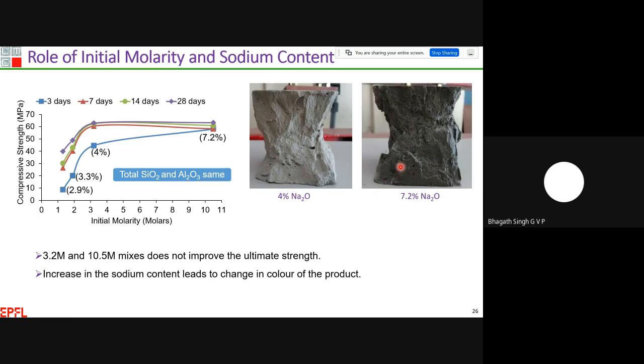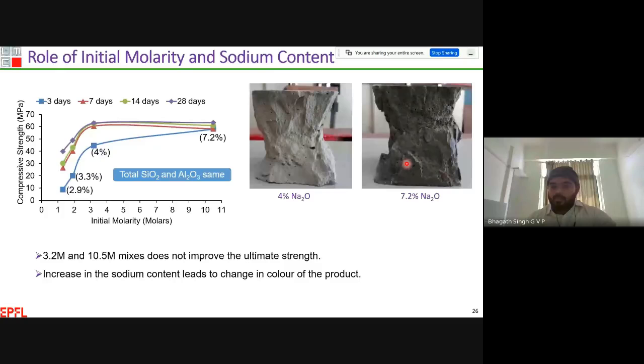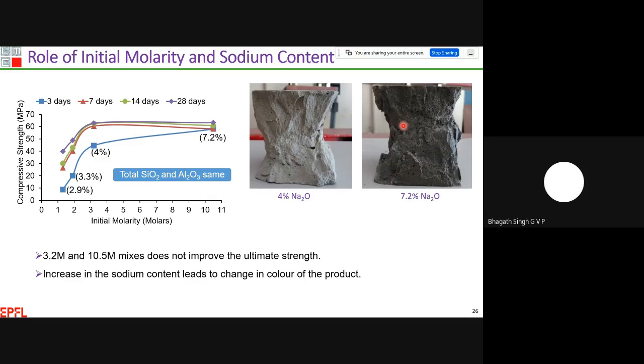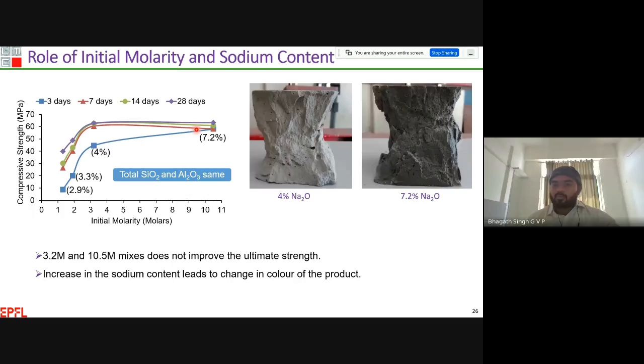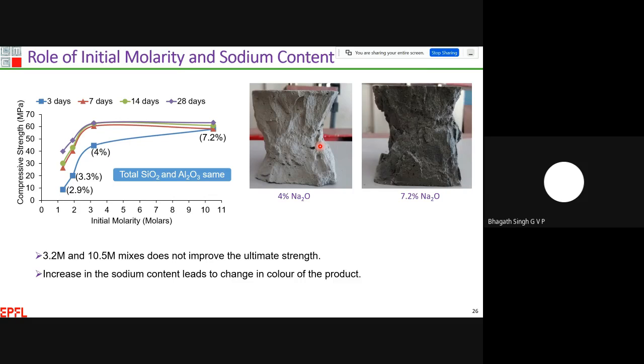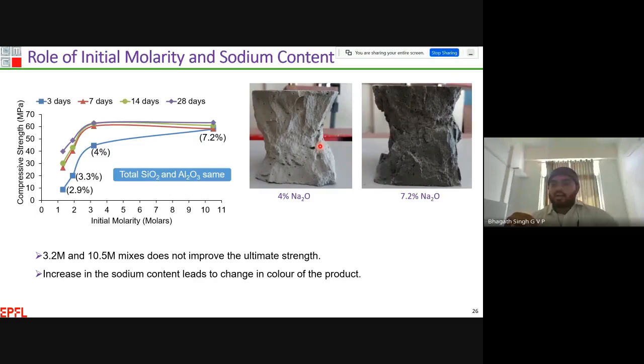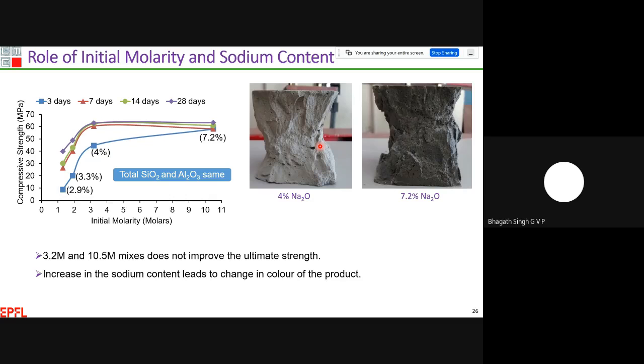sodium hydroxide solution. The increase in the molarity from 3.2 to 10.5 molars clearly enhanced the color change, but without affecting the compressive strength. In both specimens we have achieved about 62 megapascals, but increasing the molarity from 3.2 to 10.5 molars only helps to change the color of the product rather than increase the compressive strength. Which means that we should have a certain quantity of sodium content and also a certain molarity in the system, rather than blindly adding 10 molars, 12 molars, 14 molars to the activated materials.